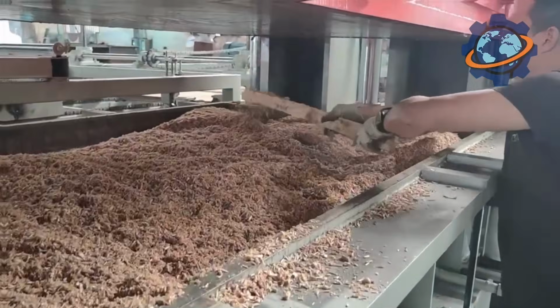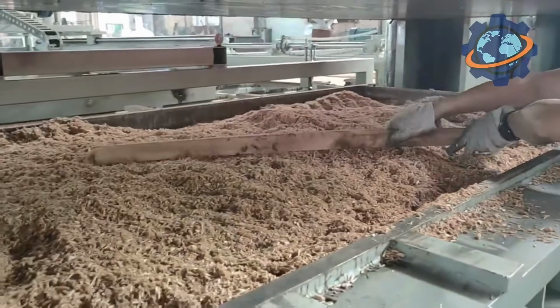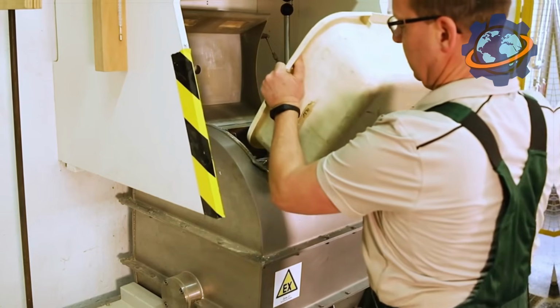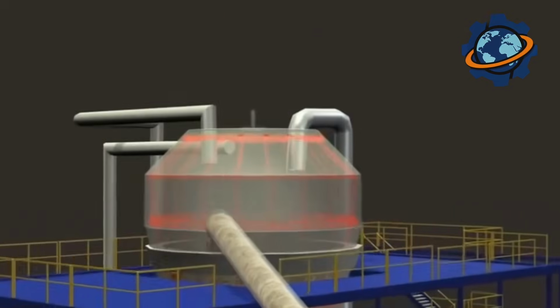If the chips are over-dried, they will not be properly saturated with glue. If they remain too moist, during hot pressing, the excess water vapor can rupture the board from the inside, forming defects. The dried chips are not uniform in size.